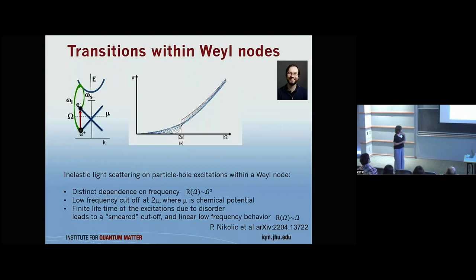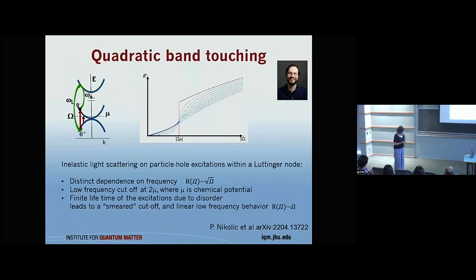If we have a chemical potential, then we have some cutoff. If we get some kind of impurity scattering, then this cutoff will be washed out. It can be very easily distinguished from the quadratic band touching, or transitions between quadratic bands, because those are expected to have a square-root-of-frequency dependence.